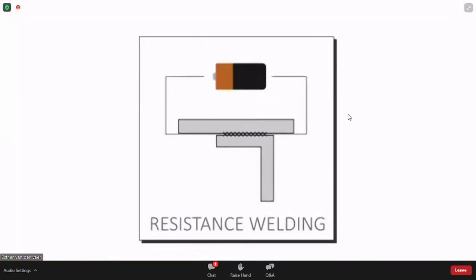Second one could be, for example, resistance welding, where you use a metal mesh which you place in between the two parts you want to weld. If you then apply a current to this mesh, it will simply heat up, very much like an old-fashioned light bulb. You use this heat to soften or melt the matrix material into the interface and allow it to fuse. So this is actually quite a mature technology.